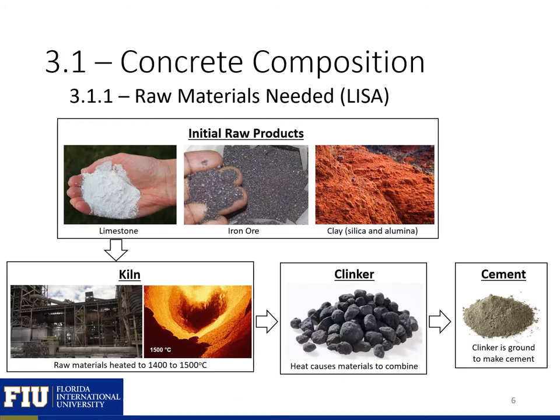The raw materials, typically limestone, iron ore, and clay, are finely ground and mixed together. The dry ground mixture is taken through a large cylindrical rotating oven called a kiln and heated to between 1400 to 1500 degrees Celsius, or about 2500 to 2700 degrees Fahrenheit. The heat from the kiln causes the material to combine into softball-sized rocks called clinker. This clinker is then ground to make cement. The fineness of the grind affects the speed of the cement hydration reaction. So type 3 high early strength cement would have a finer grind than other types of cement.